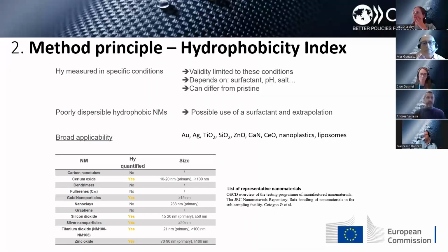What we did during the development of the test guideline, and in particular in the instructions, was standardize, during the development and the interlaboratory study, the conditions at which this measurement has to be done best. The second very important thing is that this method works also for poorly dispersible hydrophobic nanomaterials, which means they are really hydrophobic.